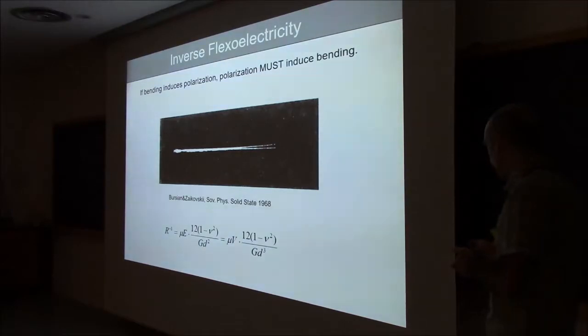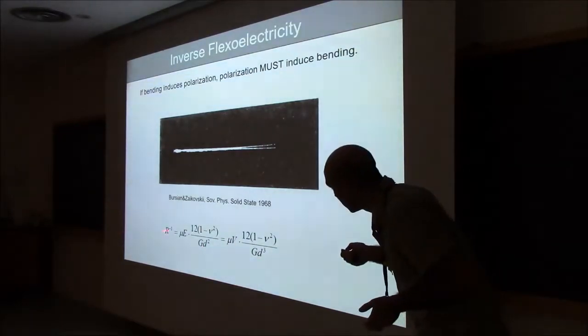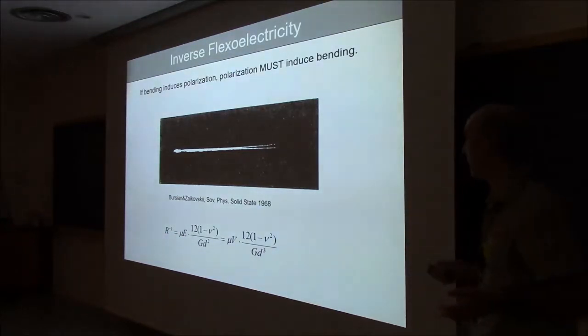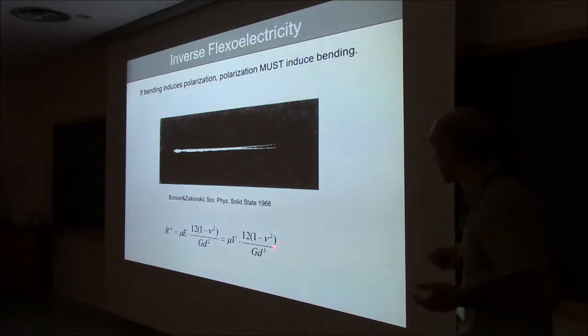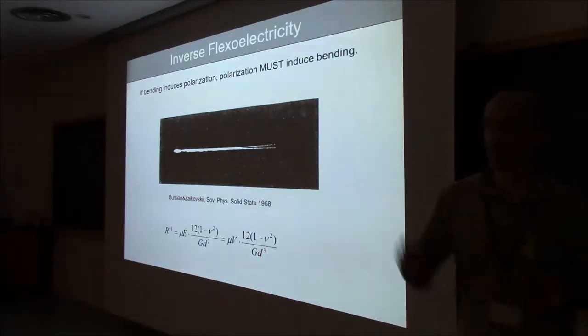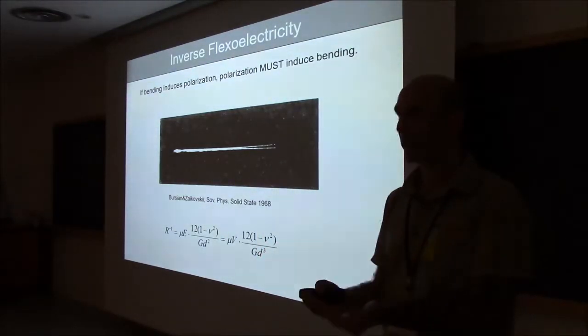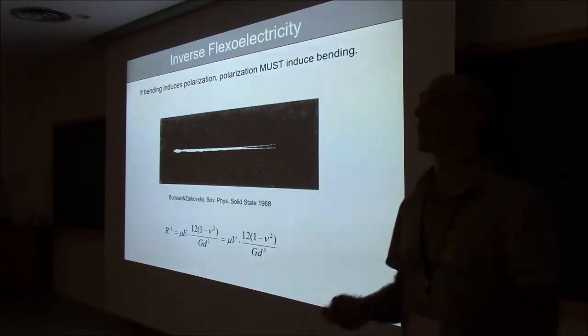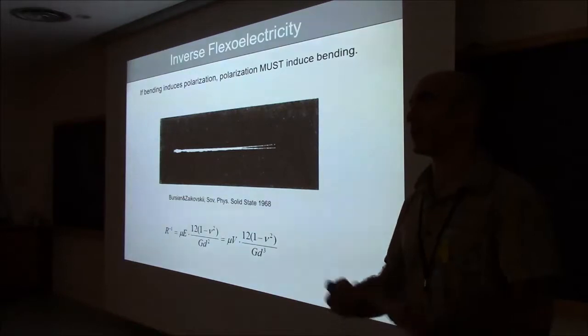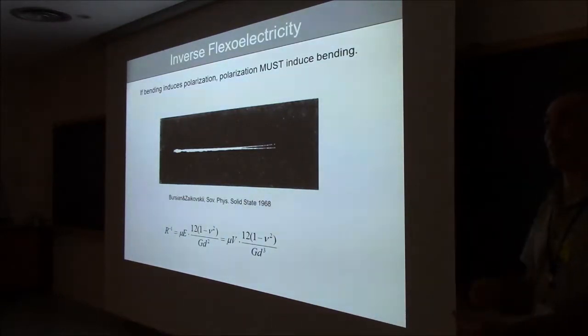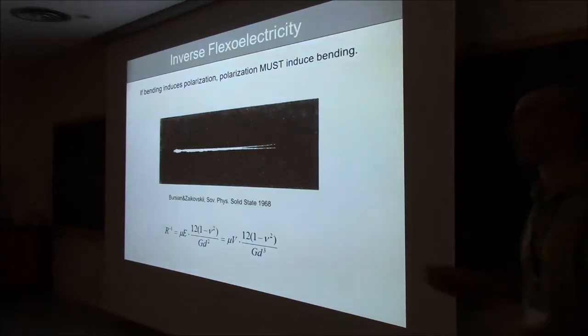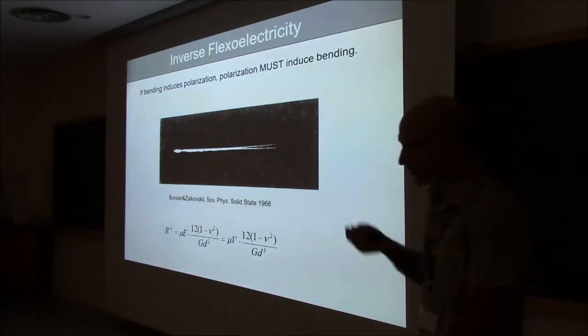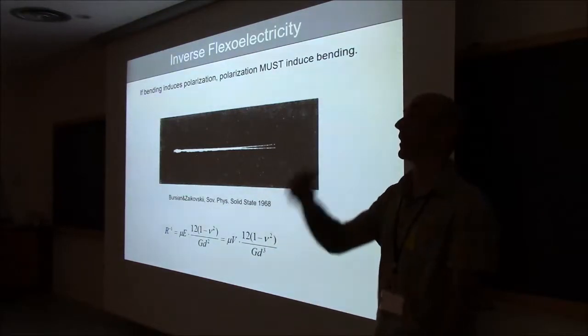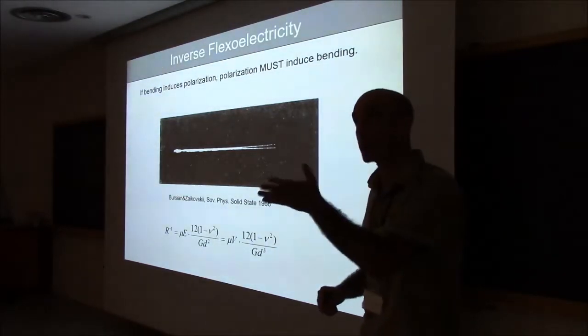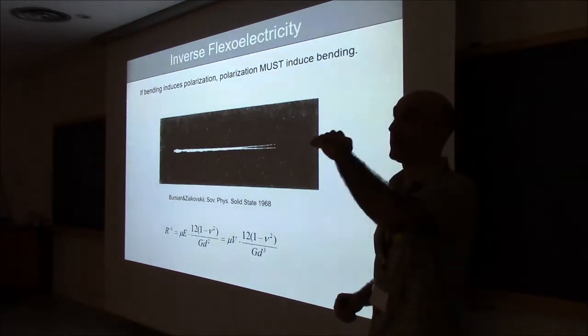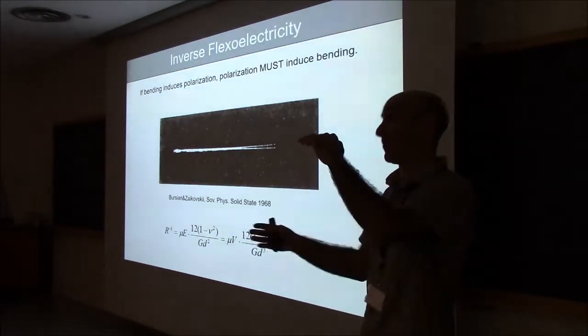Okay? In this inverse flexoelectric effect, the radius of curvature as a function of voltage goes as the inverse of the cube of the thickness. That means that every time you halve the thickness of your sample, the induced bending that you can achieve is 8 times more, so almost an order of magnitude more. Conversely, every time the thickness doubles, the effect is 10 times smaller, which means, for practical purposes, if you take a strontium titanate single crystal and you put 2 electrodes and you apply 100 volts to it, it will bend, but the radius of bending is more or less comparable to the radius of the Earth.